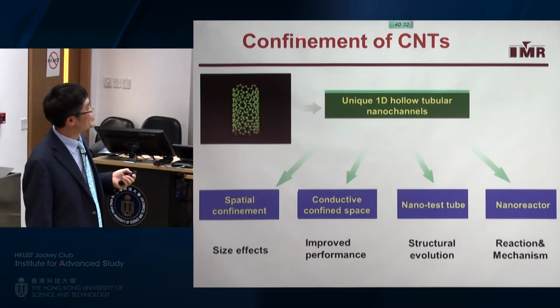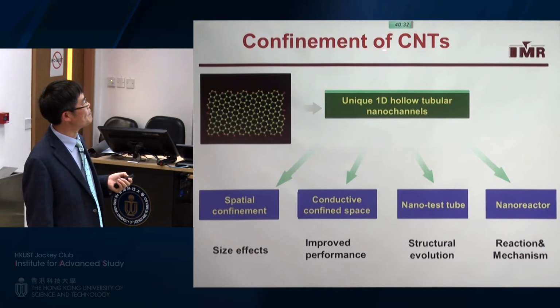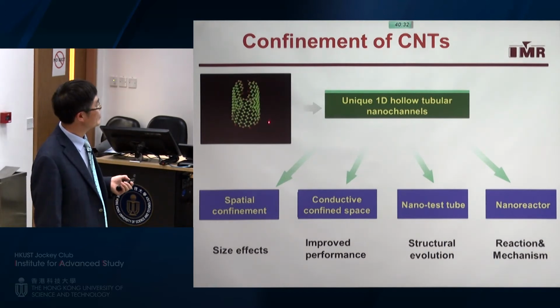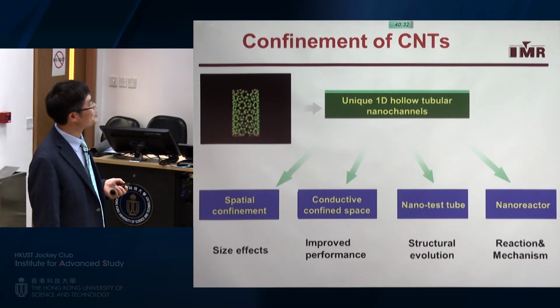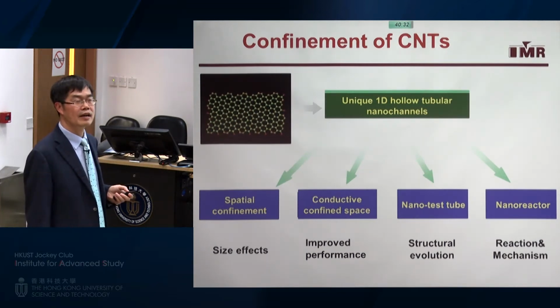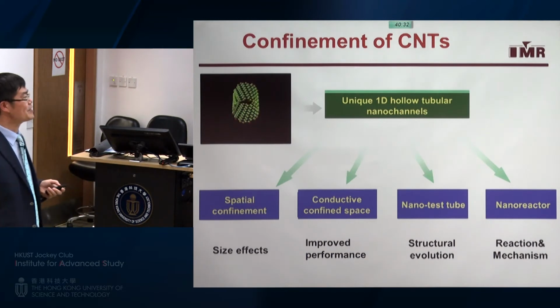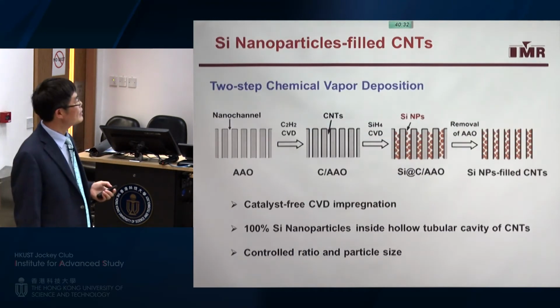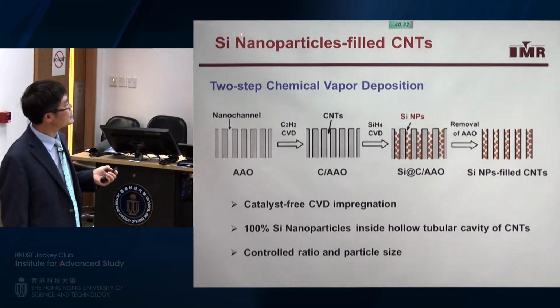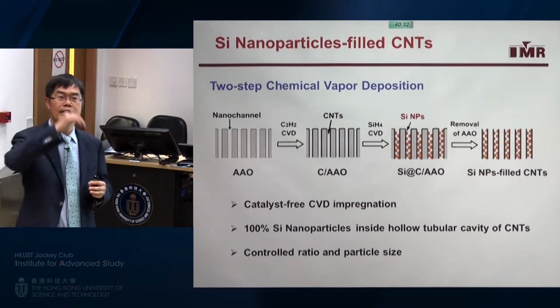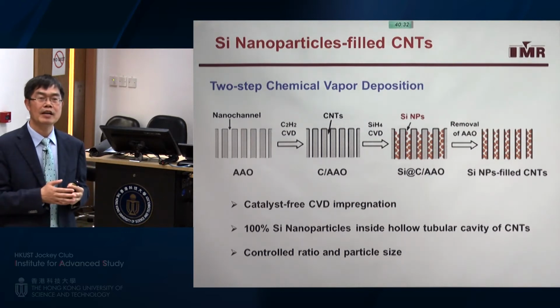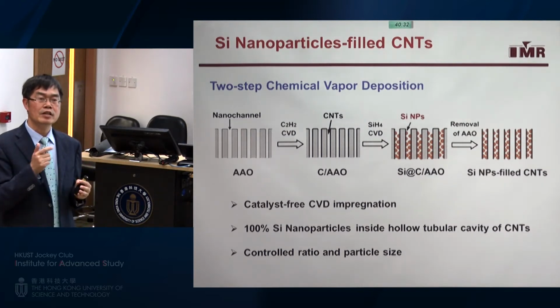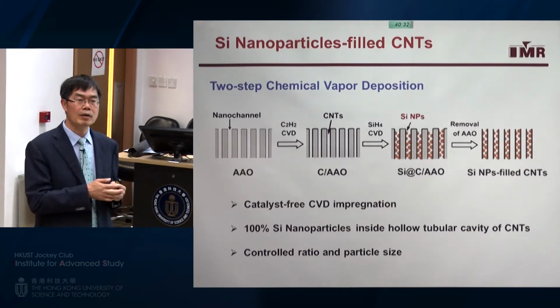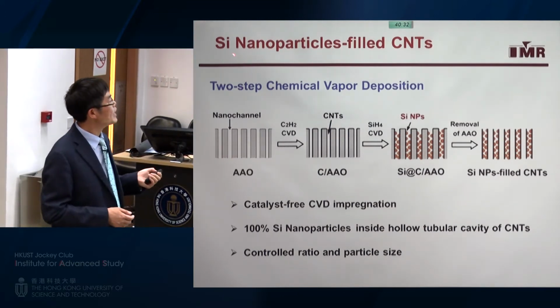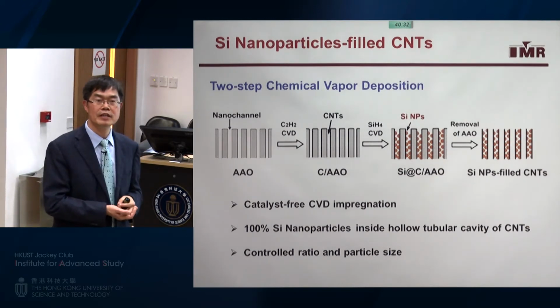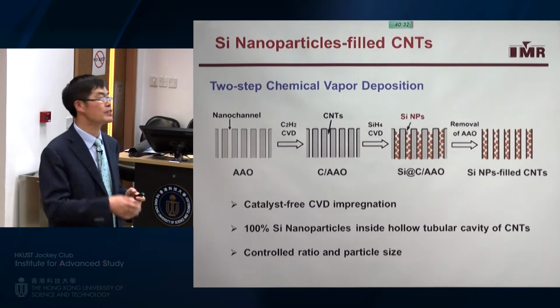Another aspect is to use the confinement effect of carbon nanotubes. Then we can also improve the performance of active materials. We know that, for example, silicon has very high capacity compared to carbon. Carbon's theoretical capacity is 372 milliampere hour per gram. But silicon has a theoretical capacity of 4,200. It's more than 10 times higher.